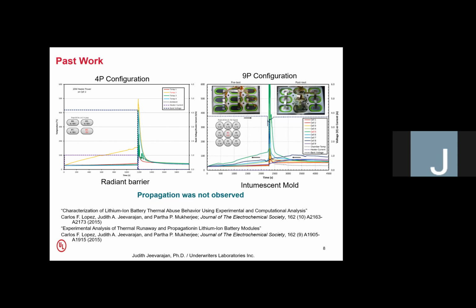And we also looked at intumescent materials. The radiant barrier was actually a sample that was sent to us from one of the NASA contractors, so after testing it, we had to return it to them. And it's not used in general for battery design. It's actually used for space applications. And then we also looked at an intumescent material, where we were able to prevent propagation, but the material itself was twice the mass of the cells that we had in that bundle. Our results are published in 2 papers in the Journal of the Electrochemical Society, and I have the reference here for you to look at later.